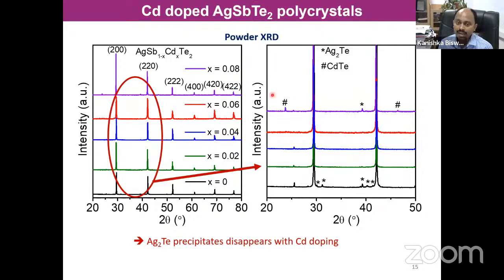But as soon as I dope 8 mole percent of cadmium, you see a peak of cadmium telluride come up. That tells us this system can take only 6 mole percent of cadmium. After that, the solid solution breaks and goes to a phase separation of cadmium telluride. So the 8% sample is also no good. We have to work in this regime of 2 to 4 mole percent of cadmium doping, which is a very low percentage of doping.